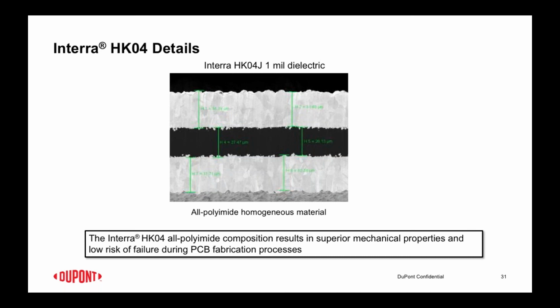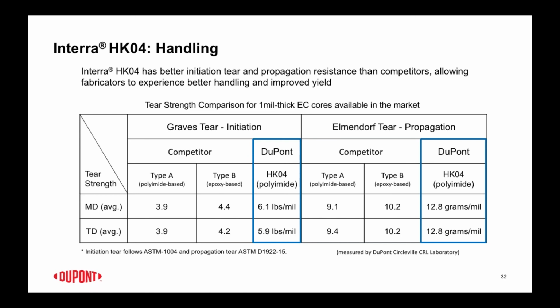In fact, most printed circuit board shops would rather process this material than the thinner FR4 materials or other competing materials. So again, we've also checked it against some others. There is at least one other 1 mil material available out there. And so compared to that, you have two things. You have tear initiation and also the ability of the tear to propagate. And again, our material is superior to anything else that's out there as far as resisting the tear from starting as well as propagating through the laminate. And again, this helps with yields and overall reliability.